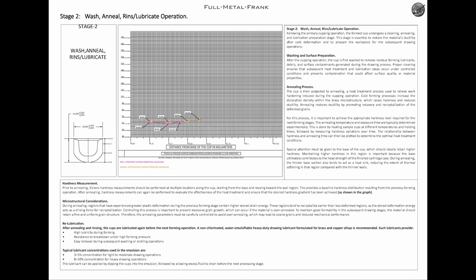Hardness measurement. Prior to annealing, Vickers hardness measurements should be performed at multiple locations along the cup, starting from the base and moving toward the wall region. This provides a baseline hardness distribution resulting from the previous forming operation. After annealing, hardness measurements can again be performed to evaluate the effectiveness of the heat treatment and ensure that the desired hardness gradient has been achieved, as shown in the graph.